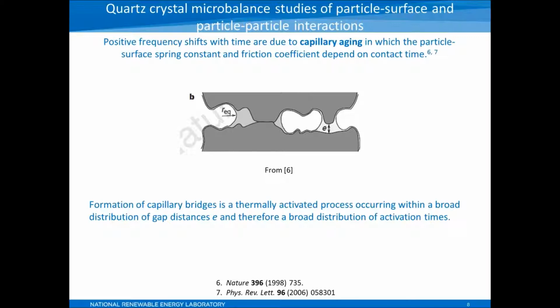The idea here is explained pretty well in this Nature paper from '98, and that's what this figure is from. Essentially, they attribute this to a thermally activated process that's occurring over a really large distribution of gap distances between asperities in the contacting region. Each one of those gap distances has a characteristic time for formation of a capillary bridge, and then you end up having usually a logarithmic dependence of the spring constant and friction coefficient with time. Reference 7 there is interesting too if you have a chance to look at it. It actually talks about a QCM experiment very similar to what I've just showed.